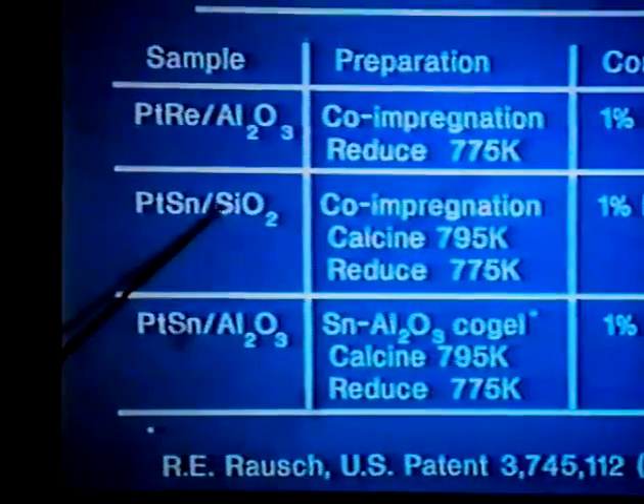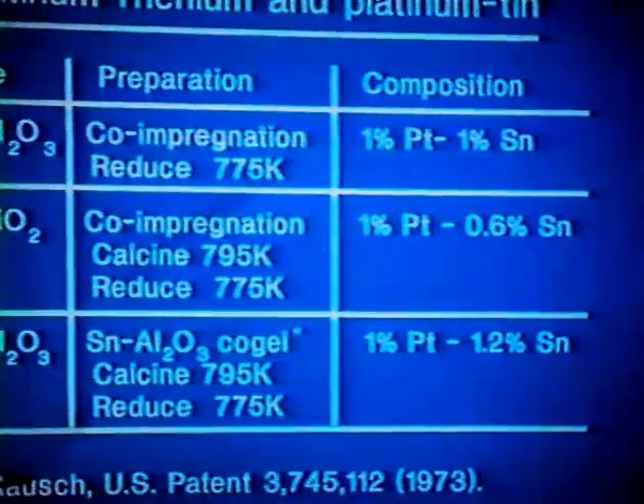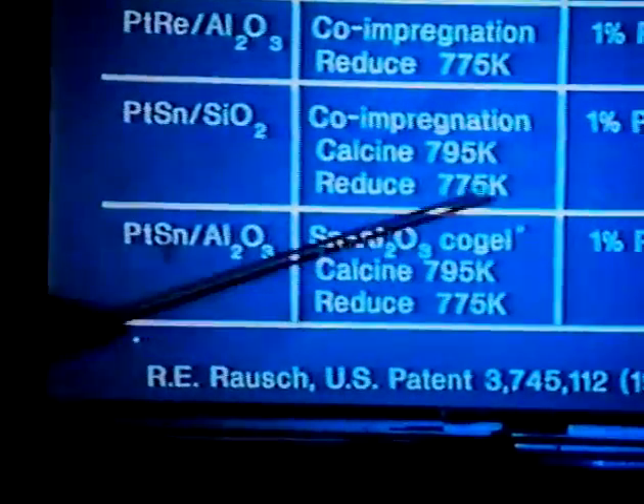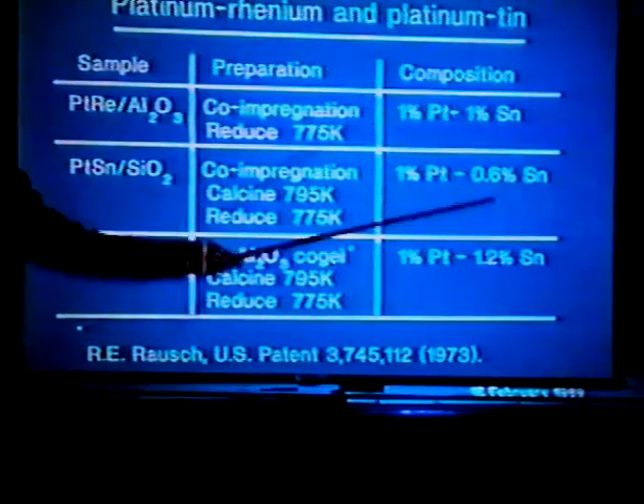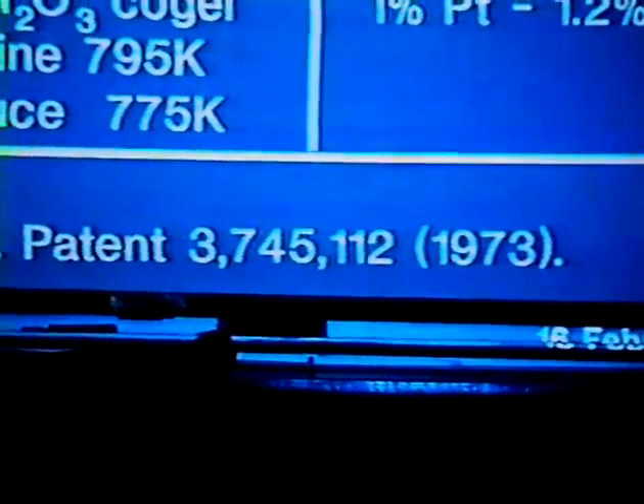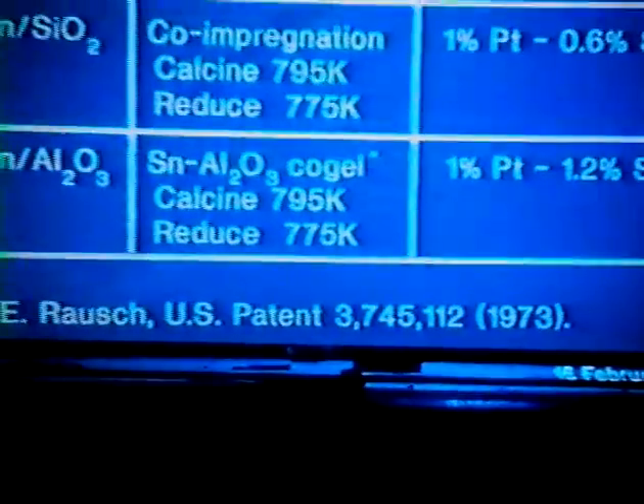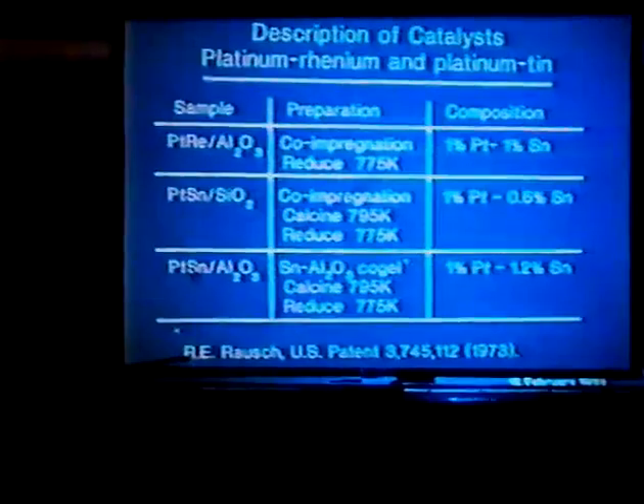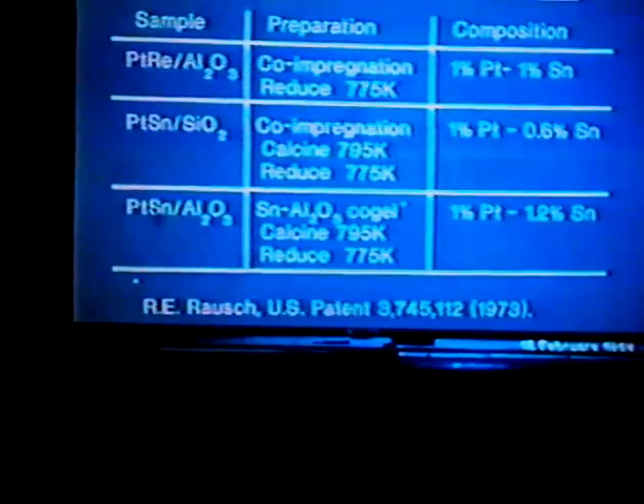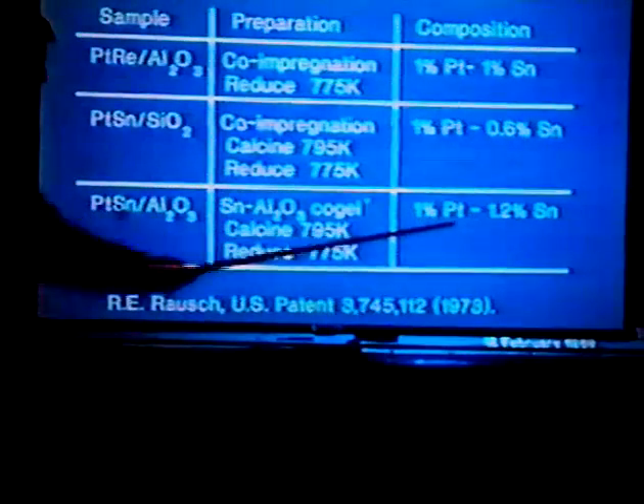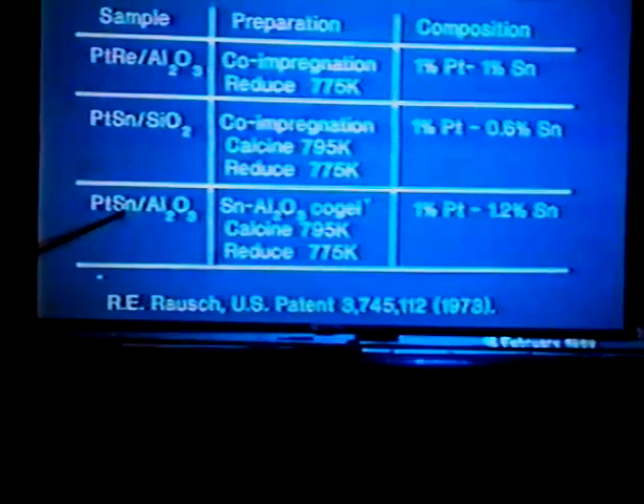Then we have platinum tin on silica, definitely not a commercial type of material. We put silica here because it's not interacting and maybe simplifies the treatment of the metals. Co-impregnation, calcined at 795 Kelvin and reduced at 775, and 1% platinum and 0.6% tin. So this is also a 1 to 1 atomic ratio. And then finally, this material, which is a quite realistic commercial type catalyst. It's platinum tin on alumina, prepared by the co-gel method, which means co-precipitation of tin and aluminum hydroxide probably, and then calcination of the gel, following the recipe provided by Rausch, UOP patent issued in '73. And it's 1% platinum and 1.2% tin. This kind of prep is designed to put the tin inside the alumina. You see, you co-precipitate them and then you calcine, you get a mixed oxide.